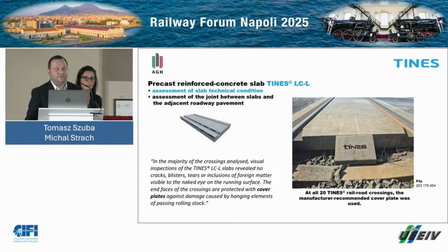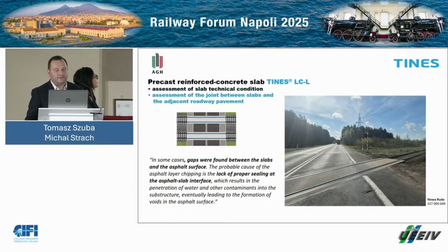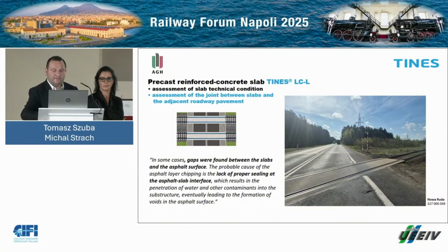The slab roadway joint is the most sensitive interface we observed. Loss of sealing allows water and fines to enter, which accelerates edge distress in the asphalt and undermines support at the slab edge. Our recommendation is to restore sealing compounds, repair adjacent asphalt, and where needed, include routine inspection of this joint in the maintenance plan.